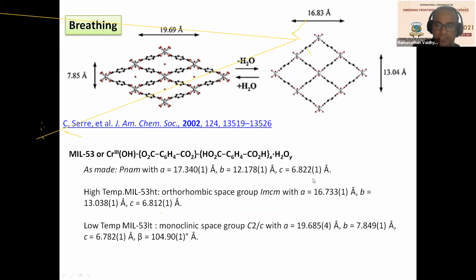People do single crystal X-ray diffraction, from which you can solve the structure. And one of the parameters that you typically follow is the lattice parameter, so A, B, and C. The parent phase is orthorhombic, solving in the Pnma space group, and has the following lattice parameters. In a cube, A, B, and C would all be the same number, whereas here they are different. Now you look at the high temperature phase of the same MOF: the lattice parameters have substantially changed, but it is still orthorhombic. And now this is representing this phase, okay?